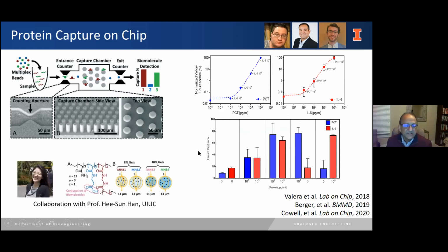And then most recently, we've collaborated with Professor Hee-Sun Han here in the chemistry department. She's an expert in microfluidic based hydrogel bead fabrication. We challenged her: can you make beads for us that have a different electrical signature without changing the size? If we change the size, we can obviously get a different impedance in this aperture as the beads pass by. But can I make the same size beads but get a different electrical signature?